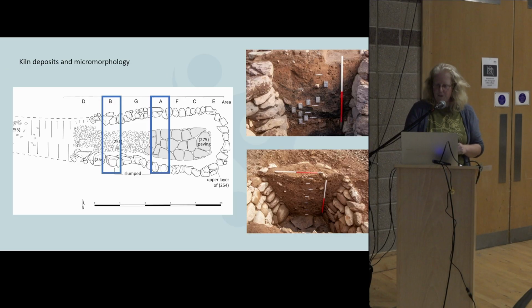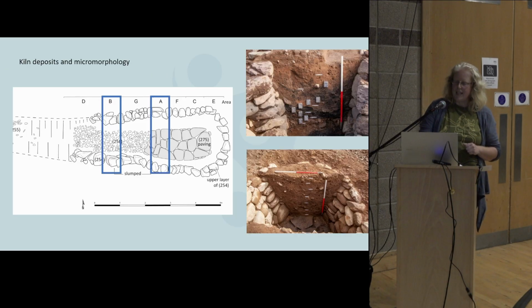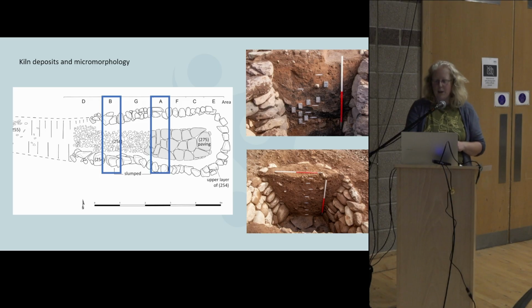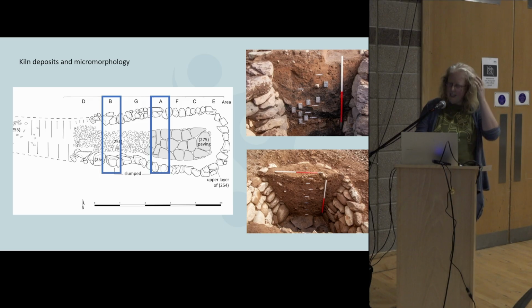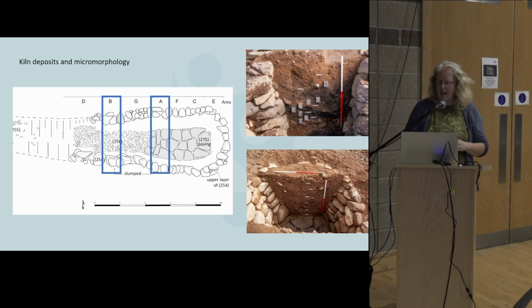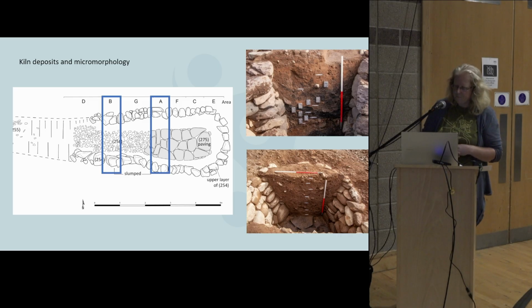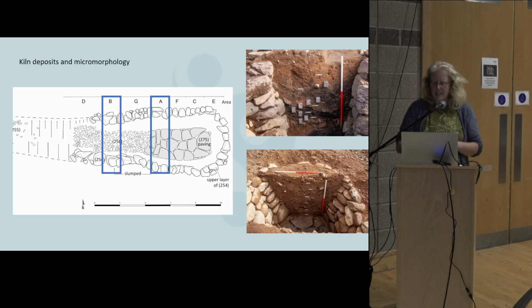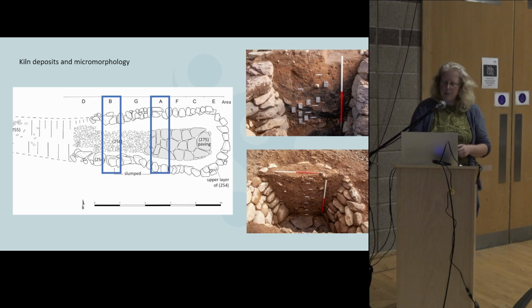So micromorphology was undertaken to better understand the infilling of the kiln, confirm if it was deliberately decommissioned and how it's degraded over time. 8 of the tins were selected for further analysis from a slot in the kiln bowl and a slot in the flue, allowing for a direct spatial comparison. Different formation processes were identified, including trampled floor surfaces and burning residues in the base of the flue, and this is in contrast to the deposits in the kiln bowl, which contain much less charred wood, but did include large quantities of burnt grain.